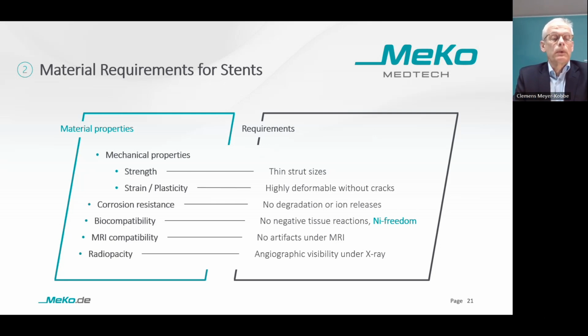With the mechanical properties, we want to ensure thin strut sizes, and the stent should be highly deformable without cracks. Corrosion resistance means we don't want any degradation or ion releases. We also don't want negative tissue reactions, which can only be ensured for all patients if the material is nickel-free. And we don't want artifacts under magnetic resonance imaging. And finally, the cardiologists want good visibility under angiography or X-ray. When we were developing the nickel-free alloy, we had to pay attention to these 5 characteristics. Finally, we succeeded in developing a suitable nickel-free alloy and called the material Vasculoy.